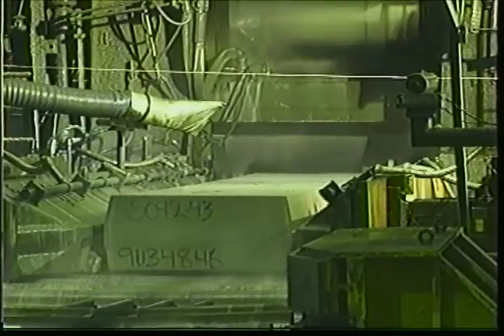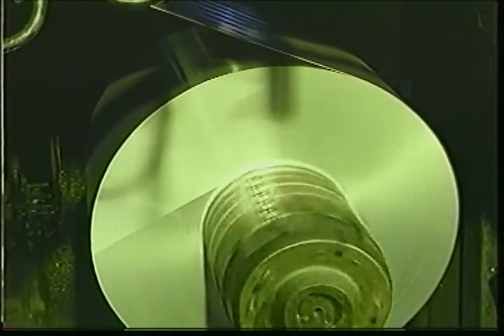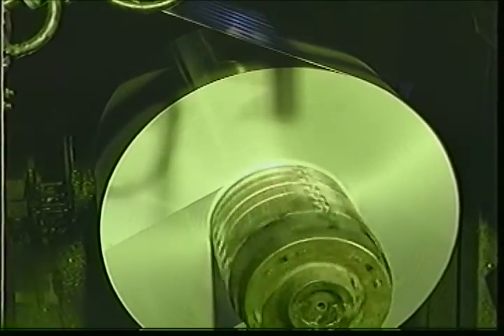After several passes through the hot reversing mill, the ingot is reduced to a thickness of 1.5 inches thick, but it is far from finished. The multi-stand continuous mill picks up the reduction process, flattening the metal to a thickness of 1/8 of an inch in less than 4 minutes. At the end of the continuous mill, the aluminum is rolled into coils, preparing for one last rolling process.